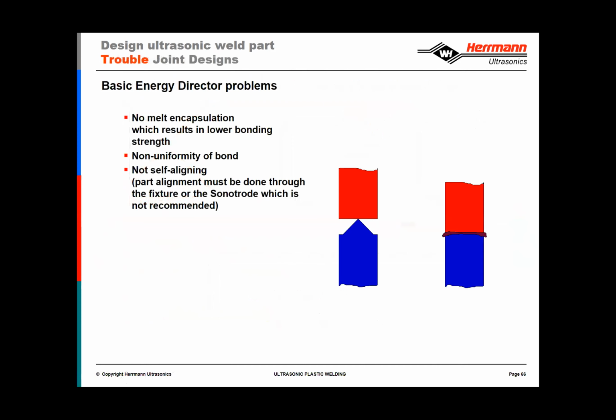So quickly turning to some of the trouble designs. And again, if you think back to the 7 points that we want to achieve, the biggest problem here is that there is no melt encapsulation. We only have one surface to bond to, and then depending on how much the weld depth is programmed for, you may see flash coming out. The parts do not self-align, so this may have to be done with either the sonotrode or the fixture, which is not recommended. But for those reasons, we typically do not recommend just a basic energy design like this one.